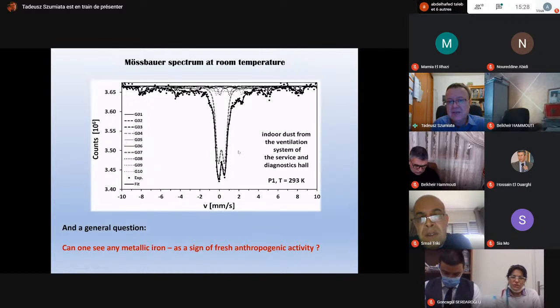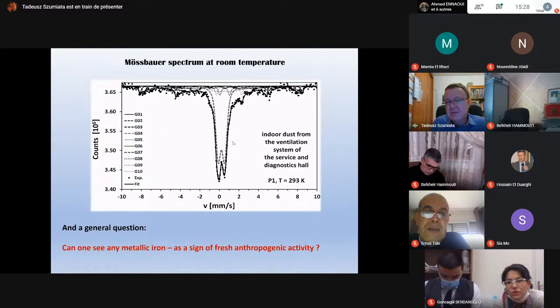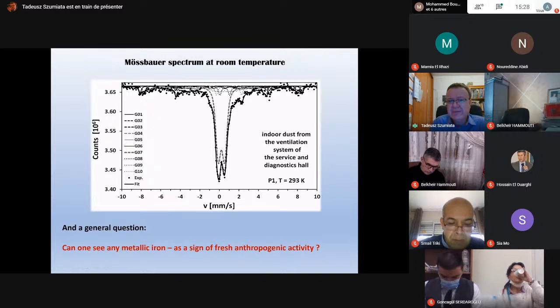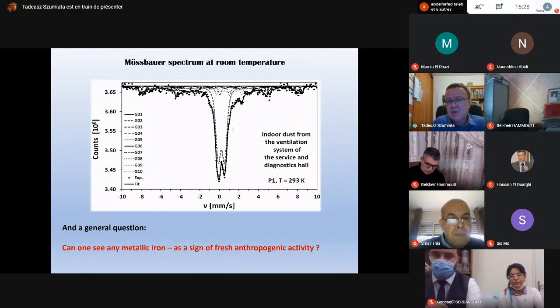And we can see a domination of such a central structure in the spectra. Probably it came from the soils, which can be incorporated inside the building just as an effect of the ventilation system and the wind, of course. But probably this very huge contribution is also connected with some very small particles of goethite, superparamagnetic particles. But the most interesting question for me was, can I see metallic iron here? Because metallic iron is a sign of fresh anthropogenic activity. And yes, we can say that there is something.